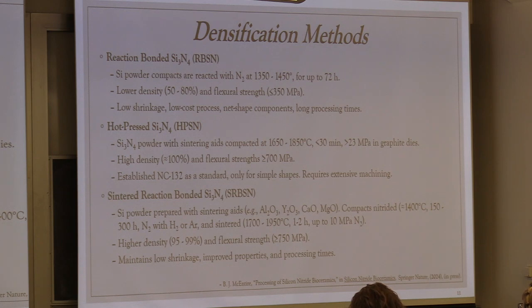The next method that came along was hot pressing of silicon nitride. The interesting story behind this one is that it also has a Utah connection. Dave Richardson, a graduate of Utah, went to work for Norton Company, and he came up with, along with a colleague there, a formula for a hot-pressable silicon nitride called NC132, which became the standard by which every other silicon nitride was judged in the 1970s, 80s and 90s, and even today it's still produced as a particular material. But the unfortunate thing about hot pressing is that it only makes fairly simple shapes, and there's a lot of machining to be done if you want to actually use it.